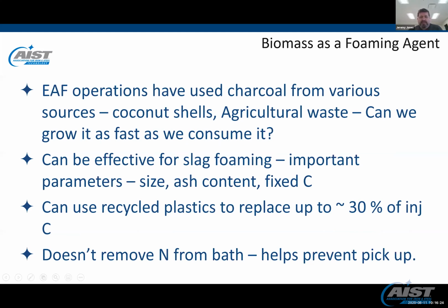Several people have looked at biomass as a foaming agent. People have used things like coconut shells and agricultural waste in Indonesia. It was fairly common to see people use roasted coconut shells as a source of carbon. So definitely people are looking at biomass as a substitute for coal. But to truly be carbon neutral, we need to grow it as fast as we consume it. So that's something that we'll have to consider. These materials can be effective for slag foaming, but of course, parameters such as size, ash content, and the fixed carbon all factor into how effective these materials can be.